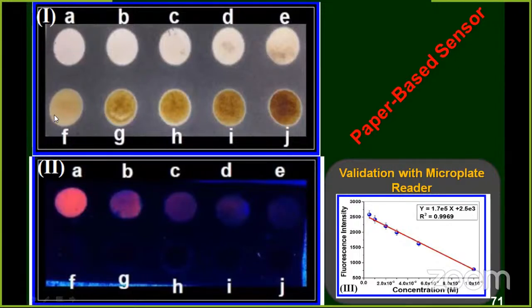So we added the nanoparticles to all the areas. This is the blank, we didn't add anything. Then we added increasing concentrations of sulfide. This is the color of Au2S. Then see here, the fluorescence is slowly quenching, and finally it disappears. We read this using a microplate reader, and we published this in that paper.